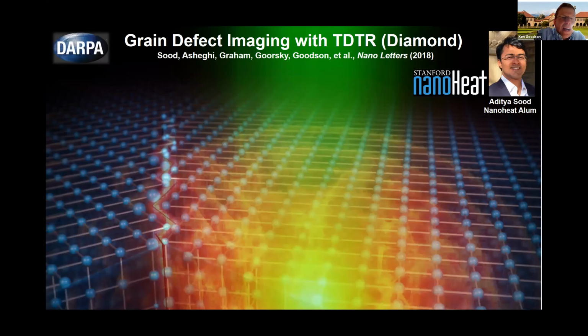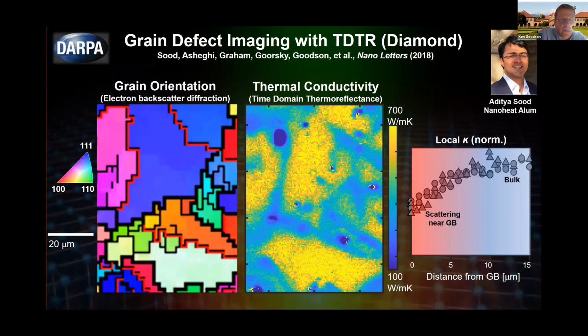In this moment, I wanted to step back and say a word more about diamond because it was part of the previous project. This is an artistic rendering of a grain boundary in diamond. And Aditya Sood, one of the great things we get to do at Stanford is mentor students from different disciplines. And so he's a material science student who got the PhD with my group. And he did a really fun measurement in 2018 where he scanned. We have a laser-based technique for extracting thermal conductivity down to a micron or so resolution. And so he basically scanned our measurement approach across the top surface of a polycrystalline diamond film and was able to map out the variations in thermal conductivity, which are high inside a grain and get much, much smaller as you get to the boundaries of the grain, and the phonons, which capture the vibrational waves in the lattice, are scattered, and this shows the grain orientation.